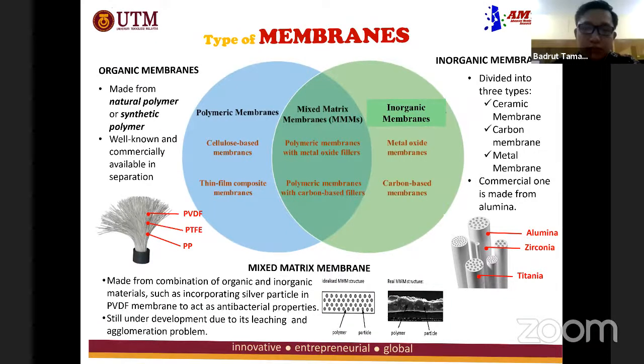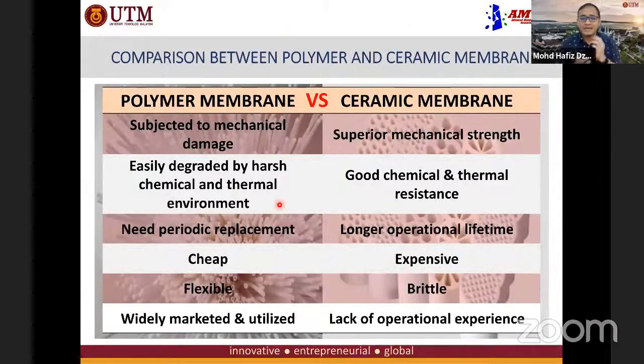So the two most common membranes in the market are polymeric and ceramic. Ceramic has advantages in terms of its superior mechanical strength and its good chemical and thermal stability. It's because the nature of the ceramic itself is very, very tough. Therefore, the ceramic membrane can have a longer operation lifetime. Normally, we can use a ceramic membrane up to 20 years, compared to the polymeric membrane, which degrades over time, and therefore we have to replace it periodically. Normally, from a period of 2 years up to 4 years, we have to change the polymeric membrane.